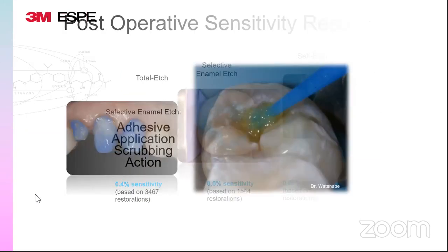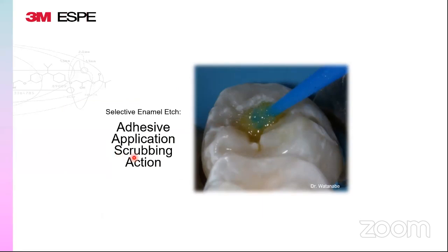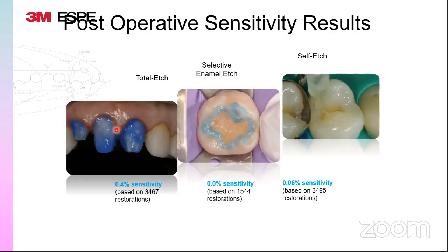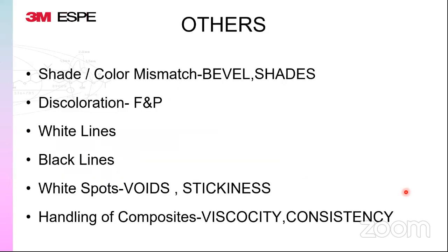Okay, I mentioned about the scrubbing action, very much required in your self-etch and your selective etch. Just a picture of total etch, what it looks like. So when I have maximum enamel, I will by default go to total etch. Some of us fear that total etch is going to give you too much of sensitivity. Next, I will try as much as possible to do the selective etch. And if these both are going to be a concern, only then I personally move to a self-etch. Having said that, if you have the good material and good technique, trust me, really, you could be doing absolutely fantastic with all the three systems. With respect to sensitivity, as I told you, 0.06% sensitivity. That's it. So negligible, or rather zero.